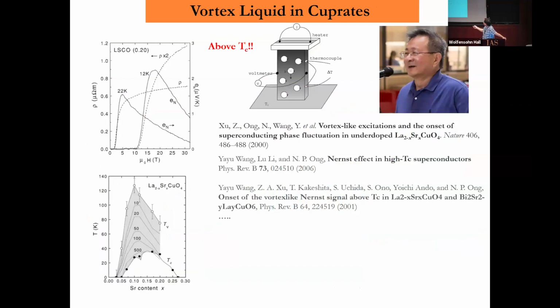This was applied to cuprates by Ong, where they found a lot of interesting phenomena, especially above TC. It's one of the early day evidence of the pseudo gap above TC. There are superconducting condensate, the vortex liquid.